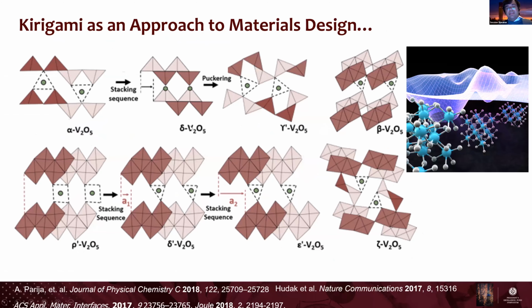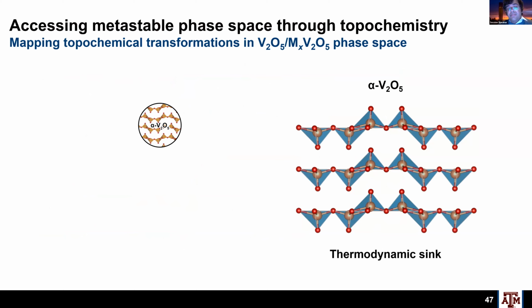And so overall, I think you could think about this as a Kirigami approach to materials design. We make MxV2O5 phases with different metal cations, and depending on the choice of the metal cation precursor, we crystallize different V2O5 frameworks, and then we can remove those metal ions. If we do it correctly, the V2O5 framework is frozen in the structure that was native to those cations, but now we can use those as frustrated coordination environments for all sorts of other cations like lithium and magnesium and calcium.